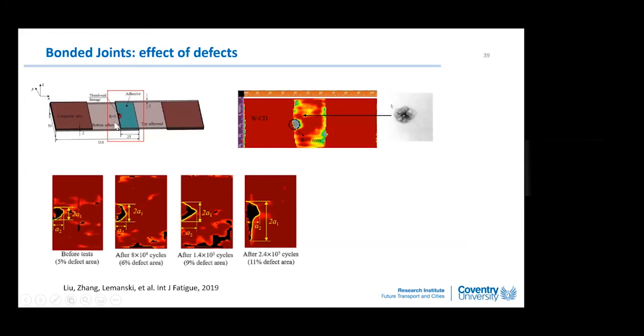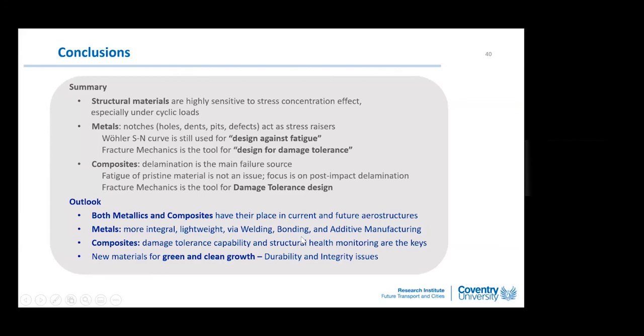The bonding line can have defects, or even damage by impact. Impact has to be tolerated. That is a runway stone hit the aircraft or people drop hammers. So we actually use ultrasound to monitor these defects in fatigue loading until they become quite large after some 10,000, 100,000 cycles.